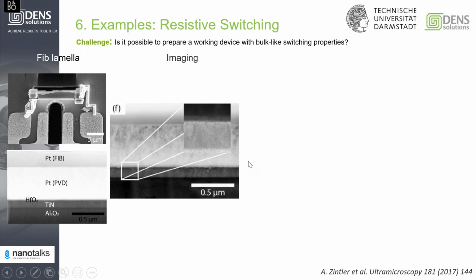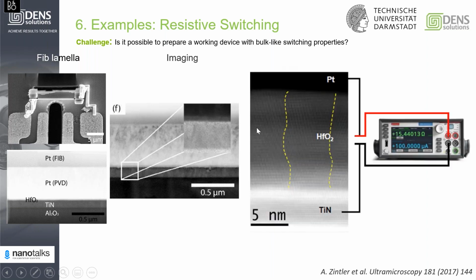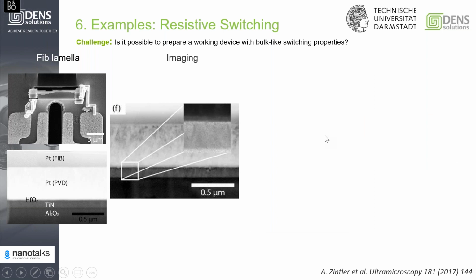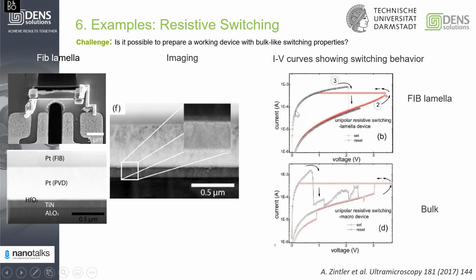So this is the TEM image. If you zoom in, you see the structure, and if you apply a bias to it in order to switch your material, basically what you can do is unipolar resistive switching inside the TEM. The black and red curves here are a set and reset curves of this FIB lamella. And actually what researchers found out is that the behavior of the FIB lamella is very similar to the bulk behavior. Which means that using lamellas, we can study bulk properties.